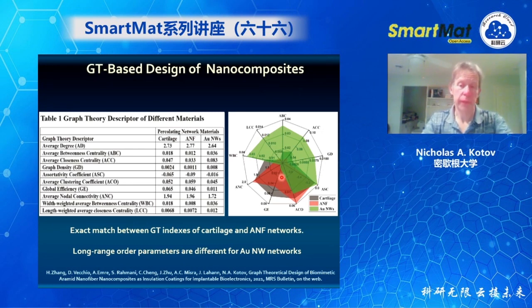At the same time, they are not the same as the networks which are made by gold nanowires. They may be better for something else, for instance, for conductivity, but they have a different long-range order and short-range order, while the cartilage and ANF are almost identical. And that proves the fact that cartilage and ANF do have the same organization. We can look at it and say, it may be the same. But here it's actually mathematically confirmed that it is true.